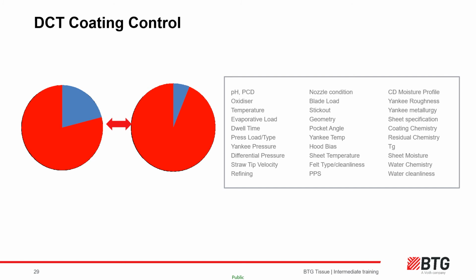Usually, however, once the coating is set up, a machine will cope with a higher but stable percentage of trash presentation to the coating, stable being the operative word. Usually this will be achieved by applying a minimum 2.5 to 3 milligrams per square metre of a modified base coat, with at least twice that of an effective and responsive release to help soften the coating layer and lubricate the blade against any hard coating layer, which could or is becoming too dominant.